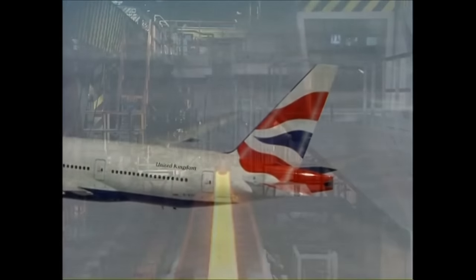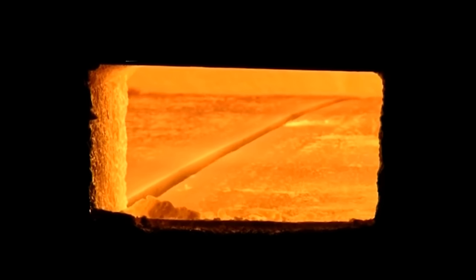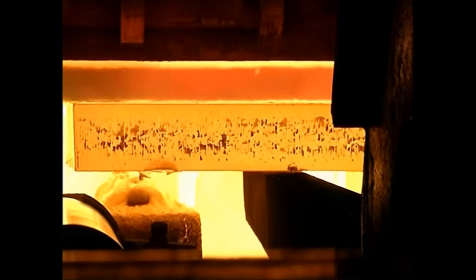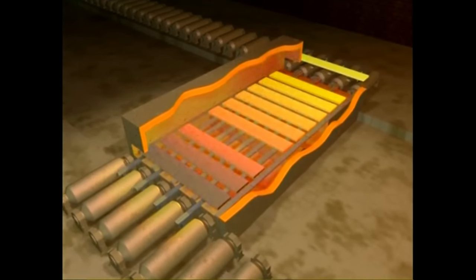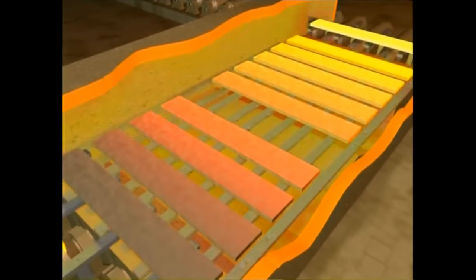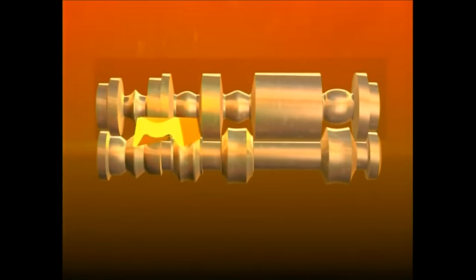Our finished products are the raw materials for thousands of other industries. Although forging and extrusion can be used to shape steel, we are mainly going to look at the principles of steel rolling. Steel is highly resistant to shaping when it's cold, and for that reason it's generally rolled whilst it's hot. To make sure the steel is at the correct temperature for rolling, it's fed into a furnace. Here it travels through several temperature control zones until it's at the correct temperature and ready for rolling. Whatever the product, the principles of hot rolling are the same.